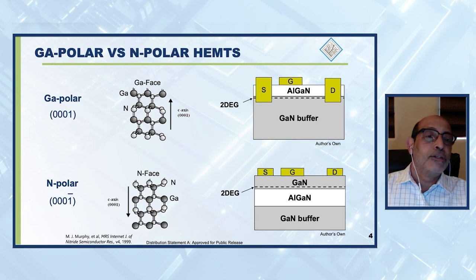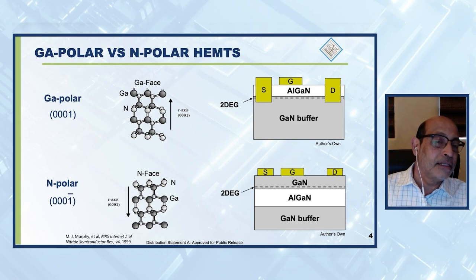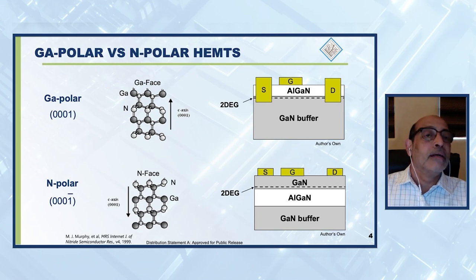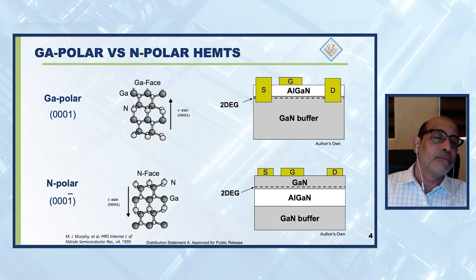When you do that, you also end up flipping where the two-dimensional electron gas, these are the electrons that carry current, is induced. In the gallium polar traditional high electron mobility transistor, aluminum gallium nitride is grown on gallium nitride, and the two-dimensional electron gas is set here. When you flip it on its head, gallium nitride is grown on top of AlGaN to produce the two-dimensional electron gas. So in one case, you have AlGaN on top of GaN. The other case, you have GaN on top of AlGaN.